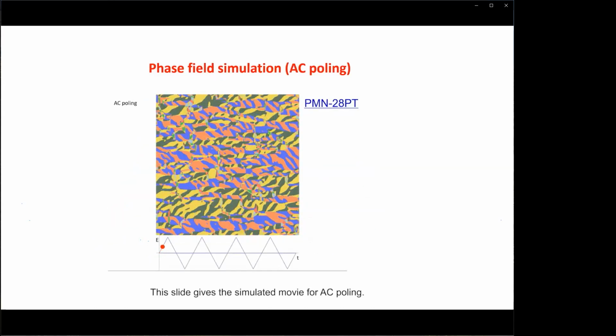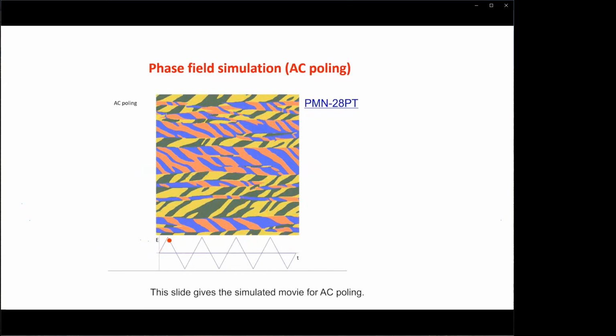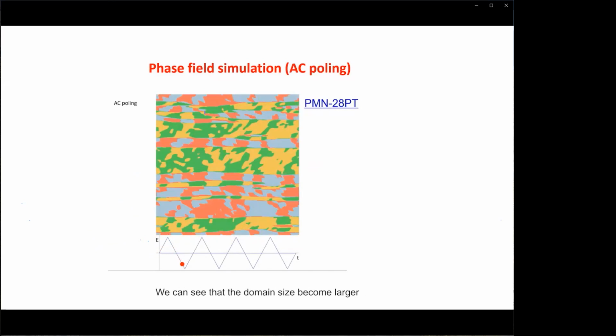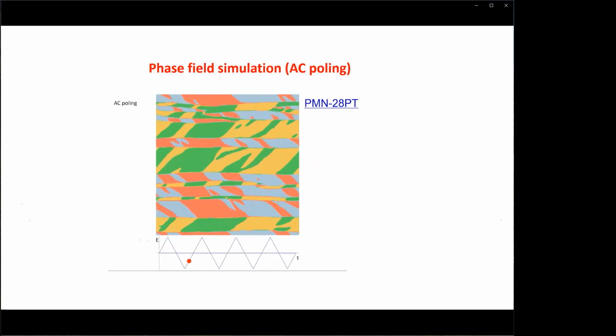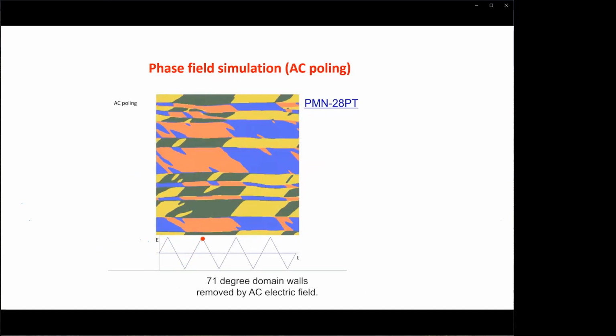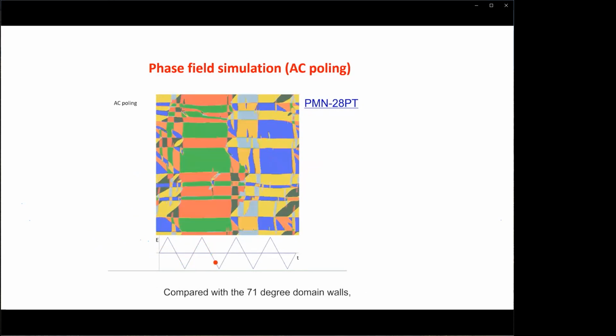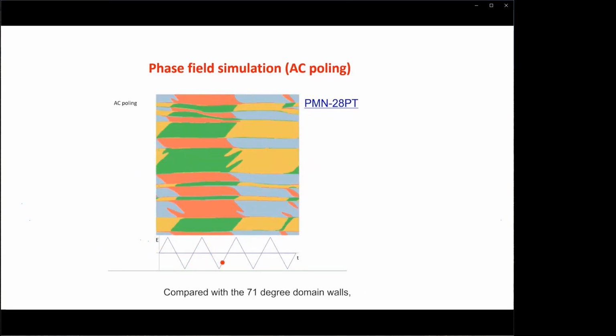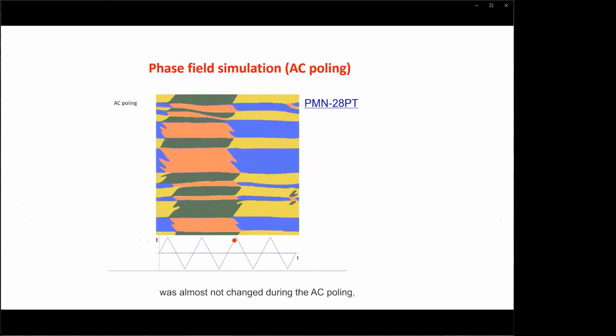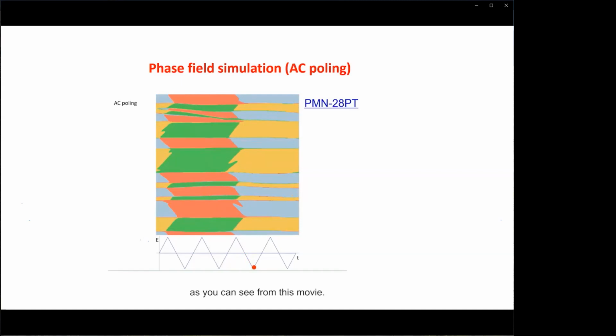This slide gives the simulated movie for AC poling. We can see that the domain size becomes larger during AC poling, and 71-degree domain walls are removed by the AC electric field. Compared with the 71-degree domain walls, the density of 109-degree domain walls was almost not changed during the AC poling, as you can see from this movie.